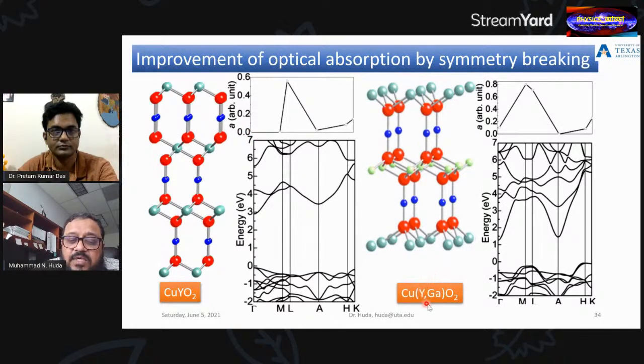Now, to break the symmetry, again, we alloy it with some isovalent atom, which is gallium. Now, one layer is yttrium, one layer is gallium, another layer is again yttrium. Because one layer is substituted by a different atom, the crystalline symmetry at a larger scale is now broken. As it is broken, at the minimum gap, where the absorption was 0, we now do have some non-zero absorption. As an added benefit, even the gap gets smaller now. So not only do we get non-zero absorption at the previously 0 absorption point, but also the gap is reduced. So this is another way to increase absorption simply from the crystal symmetry point of view.